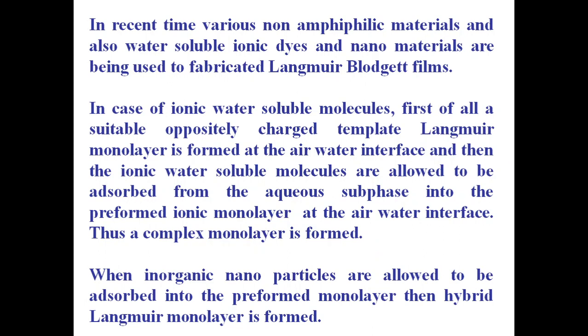And in recent times, various non-amphiphilic materials and also water-soluble ionic dyes and nanomaterials are being used to fabricate Langmuir-Blodgett films. In case of ionic water-soluble molecules, first of all, a suitably oppositely charged template Langmuir monolayer is formed at the air-water interface, and then the ionic water-soluble molecules are allowed to be adsorbed from the aqueous subphase into the preformed ionic monolayer at the air-water interface. Thus, a complex monolayer is formed. When inorganic nanoparticles are allowed to be adsorbed into the preformed monolayer, then a hybrid Langmuir monolayer is formed.